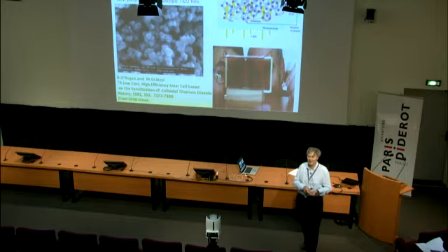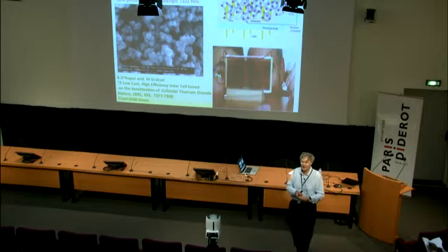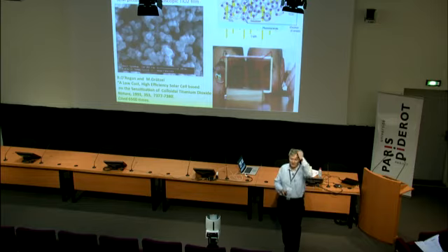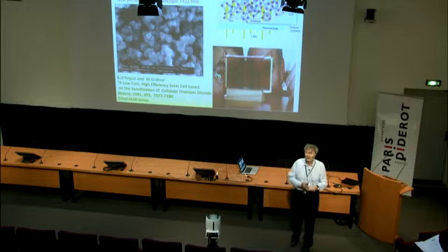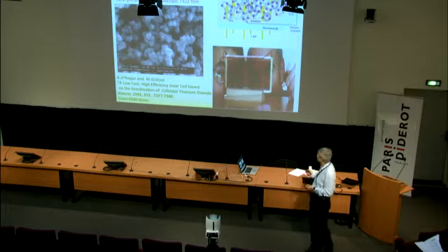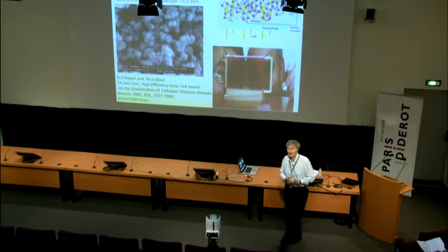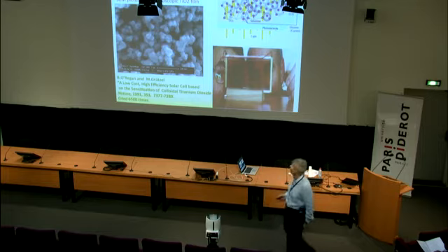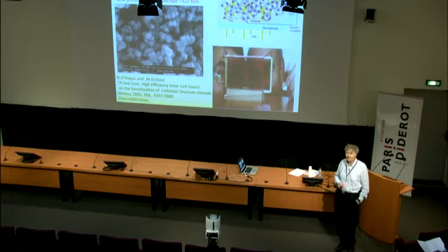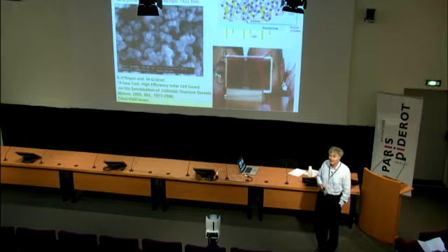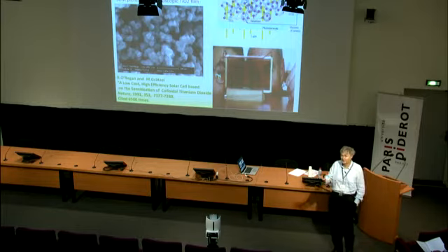And so the key parameter is the recombination time of the electrons with the oxidized redox mediator or the hole in the hole conductor. That's one parameter, the lifetime or recombination time of the charge carriers. The other key parameter, what is the time of collecting those charge carriers? And so if the collection time is 100 times faster than the recombination time, you're okay. You collect all the charges. And so impedance spectroscopy, and some time-resolved methods that have been recently developed, voltage decay methods or current decay methods, have been very valuable to get to these two parameters.